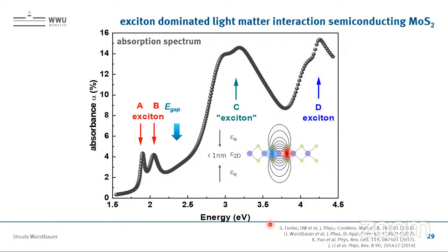What is so peculiar about the optical properties? So let me briefly explain an absorbance spectrum for this material. So it's a monolayer of these materials. You see some peak structures here around 2 electron volts, so in the visible range, which really increase to the 3 electron volt range, and also some peaks that are higher.